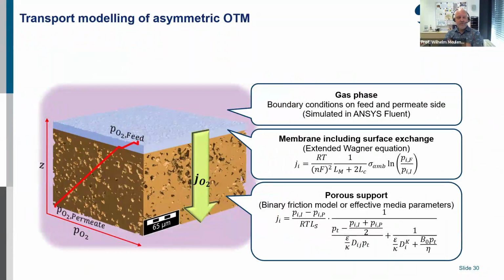Yeah, and then we made a model, because if you look at the literature, people are always looking at the materials, and then they say we have BSCF, and that is a well-performing material. It has fluxes of 10 to 20 milliliters per square centimeter per minute, and not like STF, which is maybe only below 1 milliliter, and then they decide very quickly BSCF is the best material. But BSCF is not stable in a CO2 containing environment, and STF, the strontium-based material, is stable, but it has a bad flux at low partial pressure gradients.